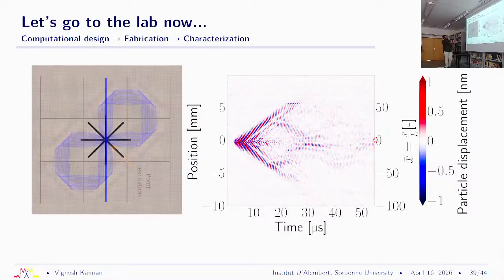The interferometer picks up the data beautifully, so you have propagation, and you start seeing that the wave amplitude decreases significantly around when your figure 8 ends, right? The other thing you're seeing here is reflection that comes in. So we seem to have some sort of back reflection. This was not predicted by ray theory, but it turns out that this is a function of frequencies that are much higher than what ray theory designed.